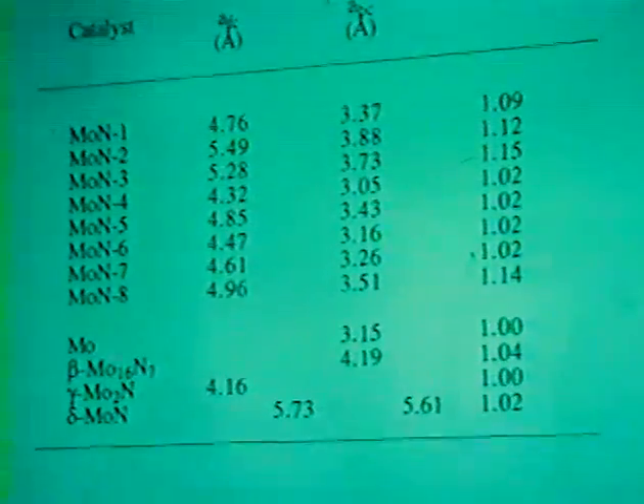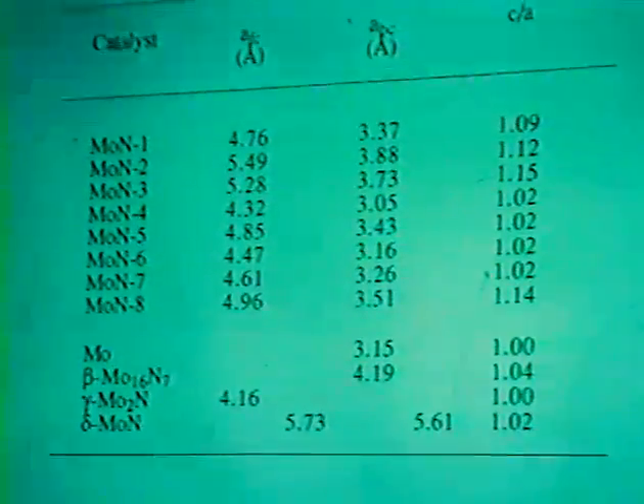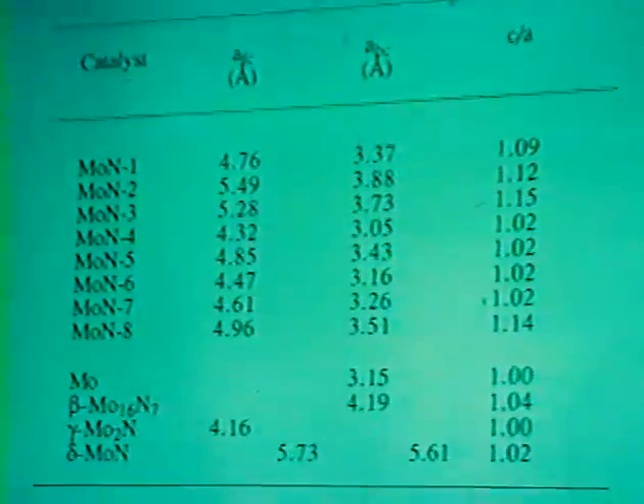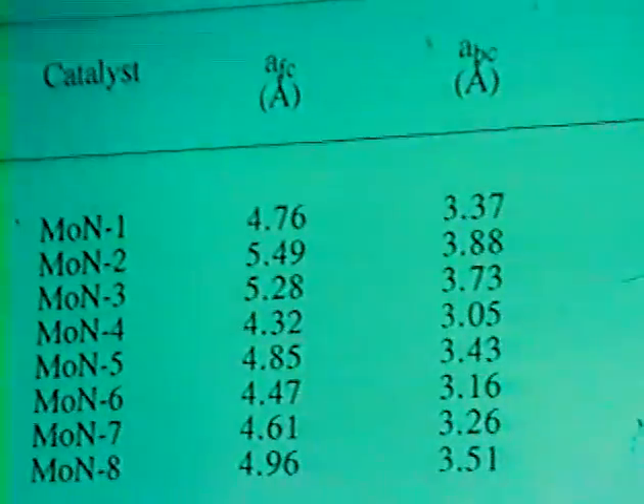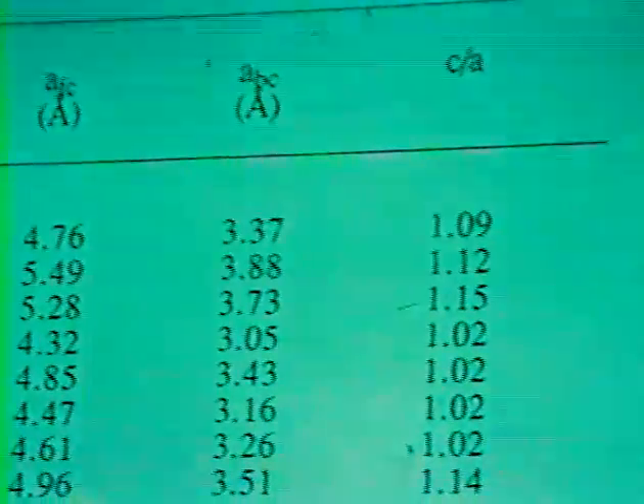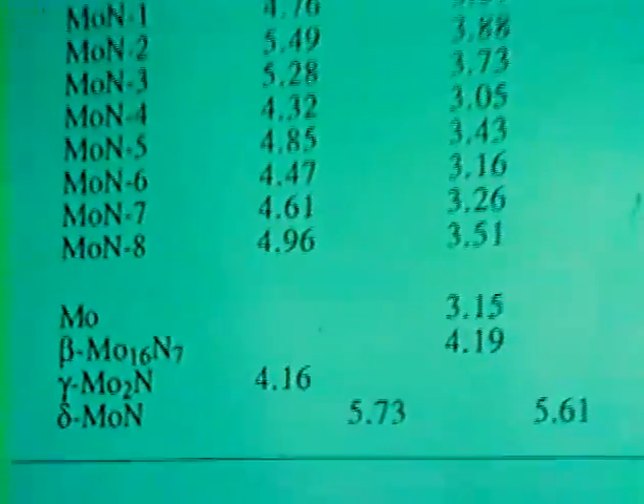And as I'll show you, these are the lattice constants that we calculate. We can either fit these to a face-centered structure or to a body-centered structure. We find that the body-centered structures are self-consistent with respect to several different zone axes, and so we believe that it is in fact near the surface a body-centered structure. You remember that the bulk is FCC. This suggests that the bulk and surface structures are very different.